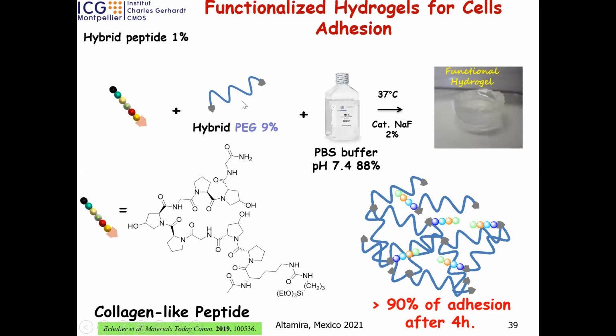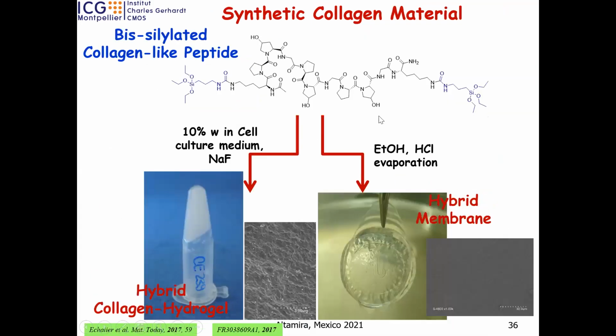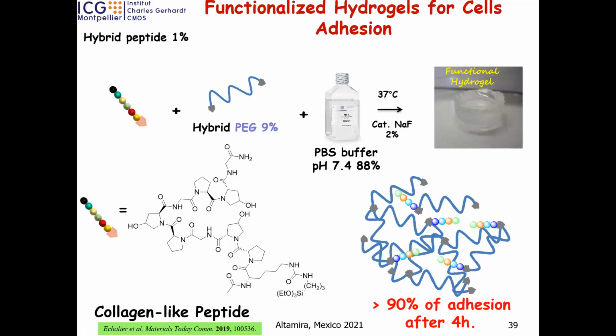Okay, another example here. We go back to the PEG, 9%, and now we mix. We take monosilylated. The idea, in order to avoid a huge amount of bisilylated collagen-like peptide, is to put only 1% of collagen-like peptide, but now it's monosilylated, with only one silane group, and we mix it with PEG at 9% and 90% of water. We prepared hybrid hydrogel materials containing both the biopolymers and the peptide. And we observe more than 90% adhesion after 4 hours.